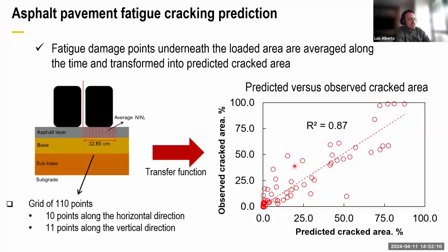Let me see if I understood your question. Here we have the observed cracked area. So we walked on the pavement and measured the cracked area. And on the x-axis, we have the predicted value from our framework. So we apply the transfer function and compare observed versus predicted. In this data set, for some test sessions we have 1 or 2 cracking observations, for another one we have 3. When we compare the cracked area for all the test sessions we have in our network, you see all predictions versus all observed ones. So maybe for certain test sessions we have 2 points, for another 1 point, for another 3 points. So this is our data set here.